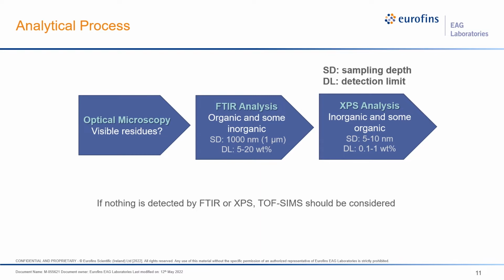So this is our analytical process. First, we take pictures to see if we notice any visible residues, and in fact, we did notice some residues on some of these wafers. The next test we do is infrared analysis. That's going to tell us mostly organic information, but also some inorganic, because there are some compounds, like silicates and nitrates and so on, that we can detect. What I want to bring your attention to is the sampling depth and the detection limit. The sampling depth here is about a micron, about 1000 nanometers, or 1 micron, for FTIR, and the detection limit is 5 to 20%.